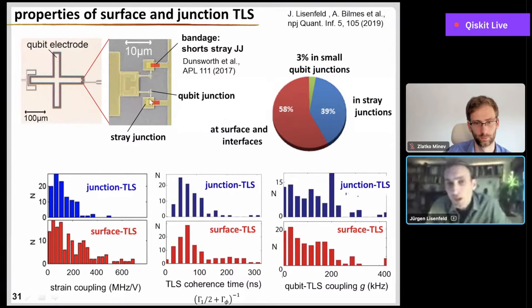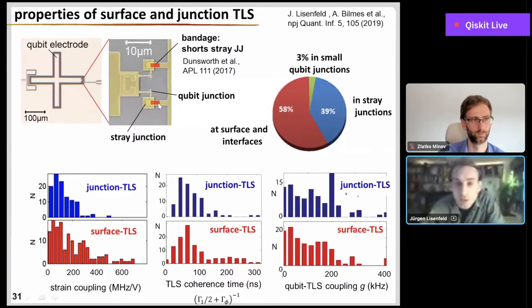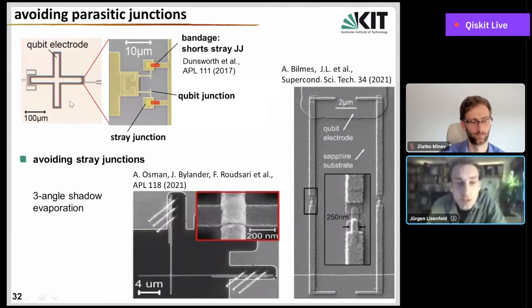Okay, however, this bandaging is a little bit of an annoyance because it requires a complete third lithography step, which likely also introduces new residuals from photoresist, for example. And just to mention it, there are now new techniques to make junctions using three-angle shadow evaporation. You can in situ, so in the same pumping step, not only deposit your junctions at two different angles, but under a third angle you can also make these connections, for example, from the junction to the electrode ground planes, or to short these parasitic junctions.